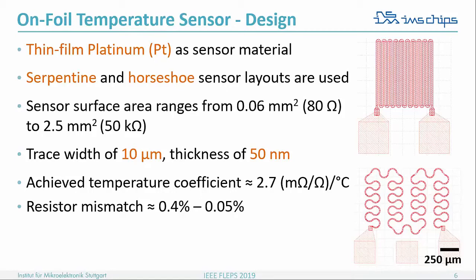The limit of the resolution of the fabrication is limited by our laser direct writer, so we do conventional photolithography. It's not printed. It's using CMOS, almost CMOS processes, and the thickness of the sensor material, its PT, is about 50 nanometer, and of course a very thin titanium layer for adhesion promotion.